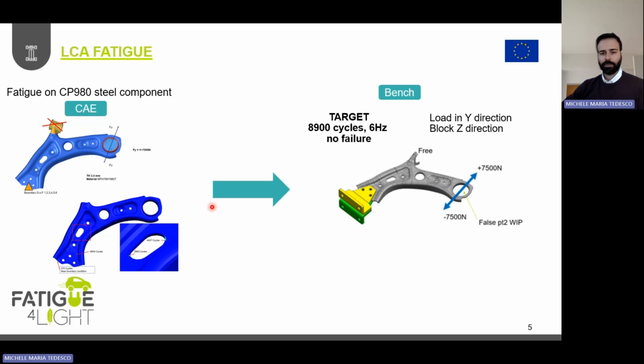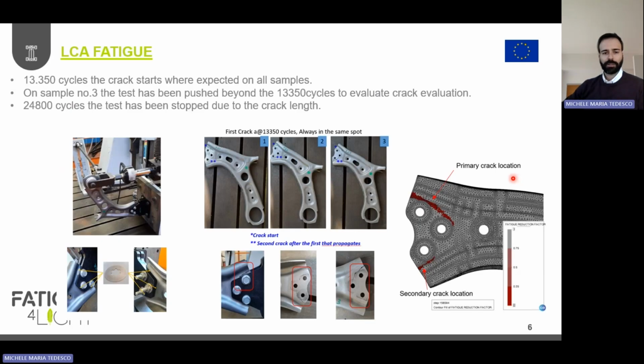Also at the bench test, we realized an equipment to block here the component, and we applied the stress plus minus 7.5 kilonewton. Here you can see the bench test characterization and the three samples that we characterize. From the real characterization, so the physical characterization, we have seen that at 13,000 cycles, the crack starts were expected from the simulation.